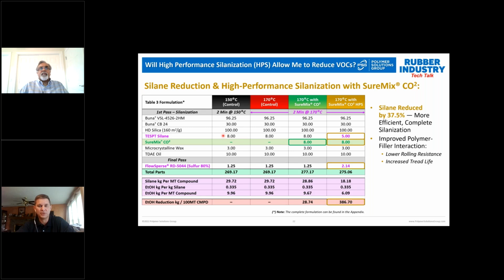One, was there an opportunity to do silanization in the mixer at a higher temperature using SureMix? Basically buying a processing window at a higher temperature because of the improved processing with SureMix. We would want to do that because by going to a higher temperature, you can drive the silanization reaction. And in doing so, you can get better silica dispersion and a further reduction in hysteresis and improved fuel economy.